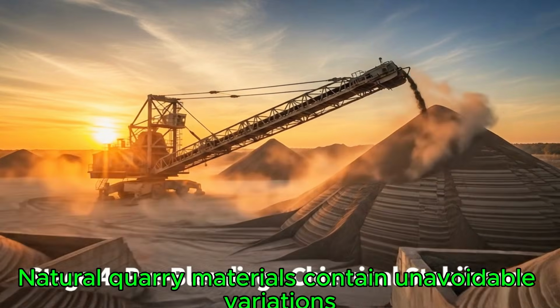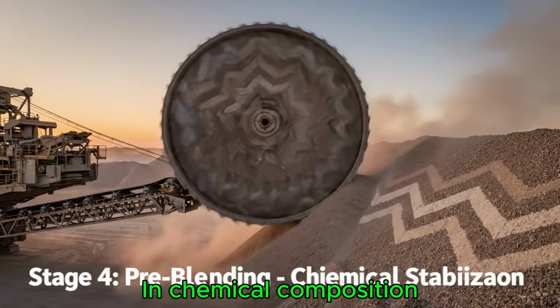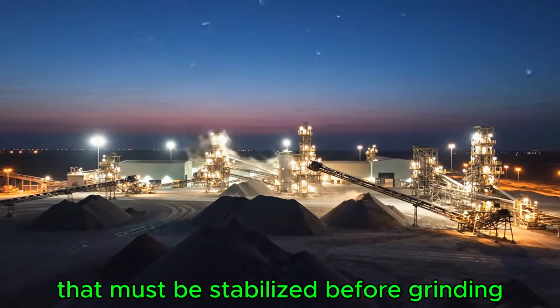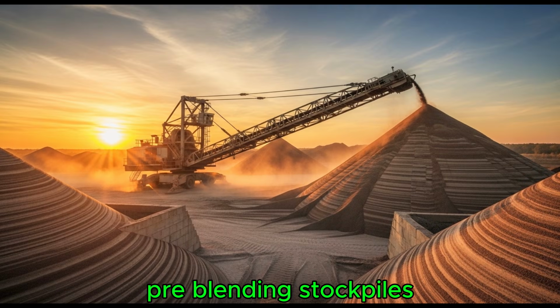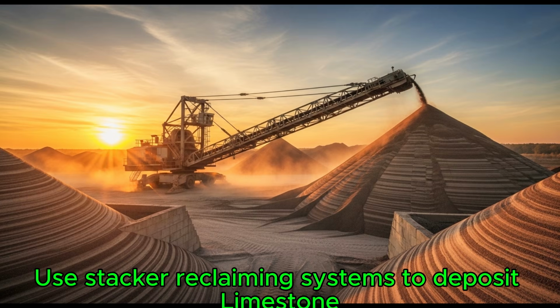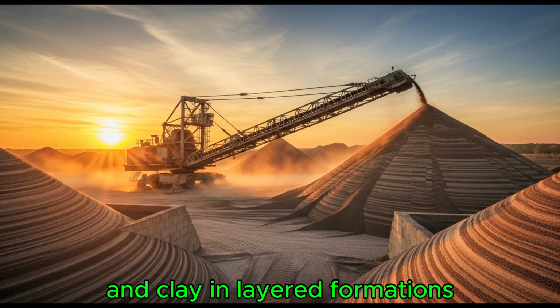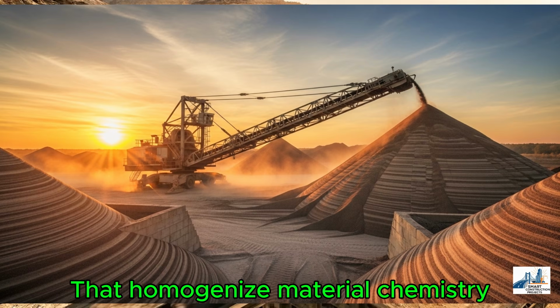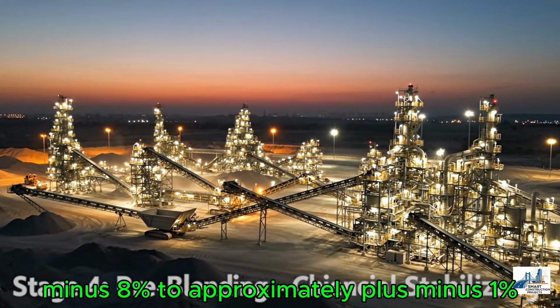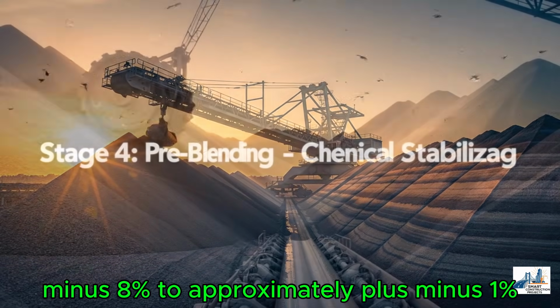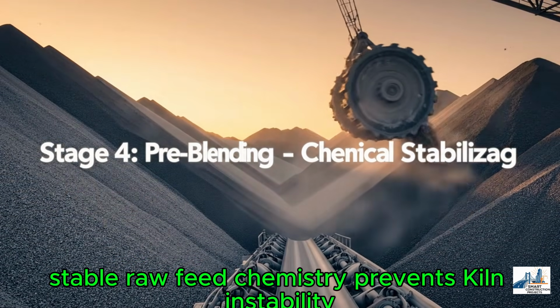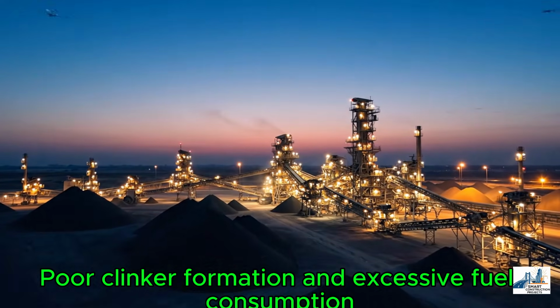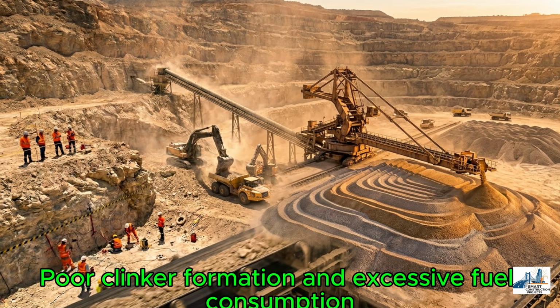Natural quarry materials contain unavoidable variations in chemical composition that must be stabilized before grinding. Pre-blending stockpiles use stacker reclaimer systems to deposit limestone and clay in layered formations that homogenize material chemistry. Controlled stacking and reclaiming can reduce chemical fluctuations from nearly plus or minus 8% to approximately plus or minus 1%. Stable raw feed chemistry prevents kiln instability, poor clinker formation, and excessive fuel consumption.